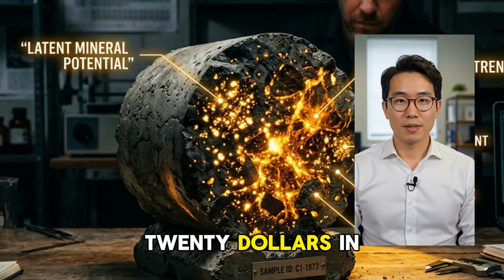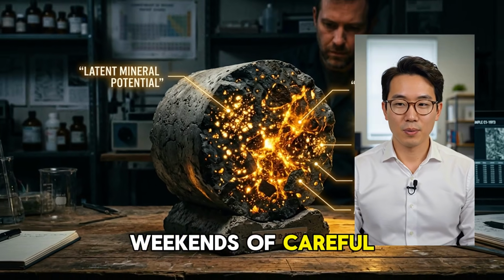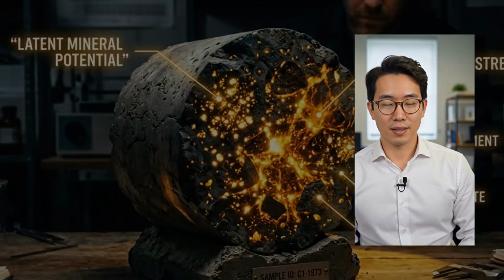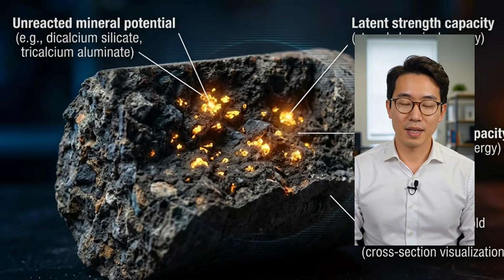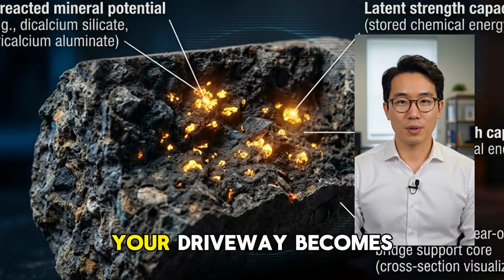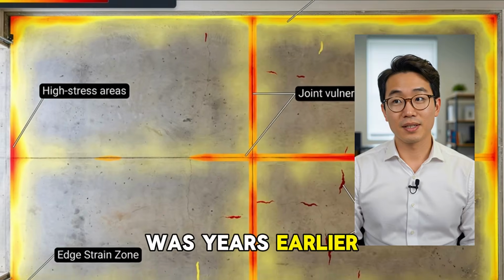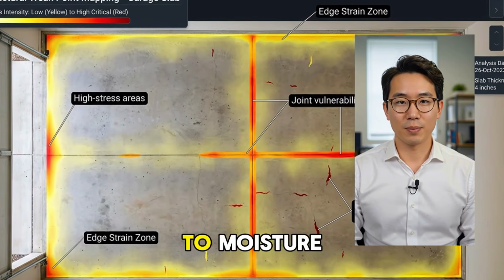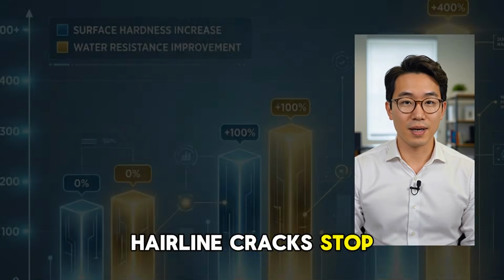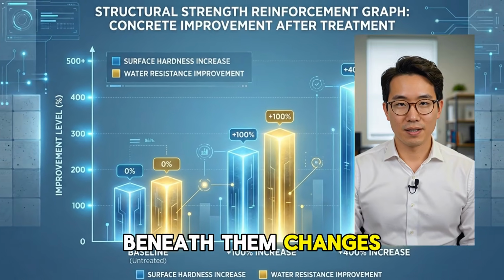For less than $20 in materials and a couple weekends of careful work, you can restore aging concrete using a government-tested hardening process documented more than a century ago. Your driveway becomes harder than it was years earlier. Your basement walls become more resistant to moisture. Hairline cracks stop spreading because the chemistry beneath them changes permanently.